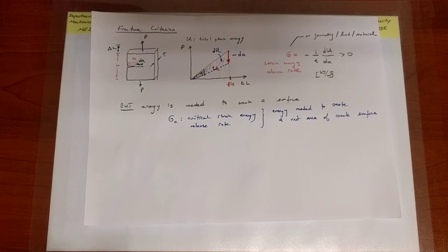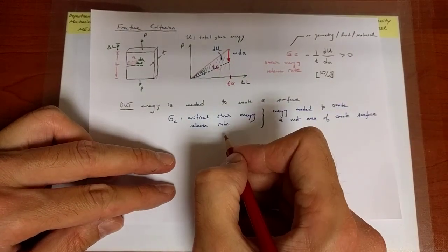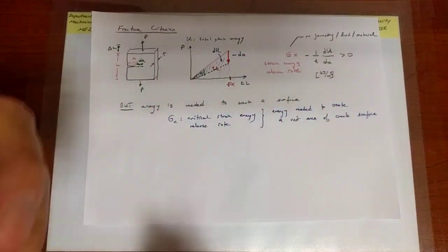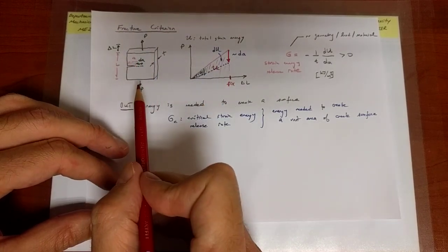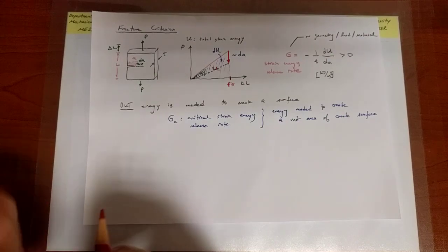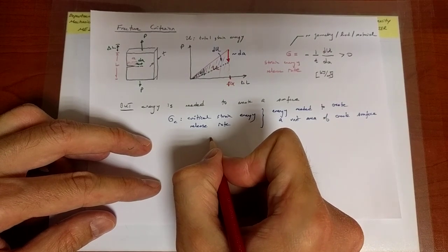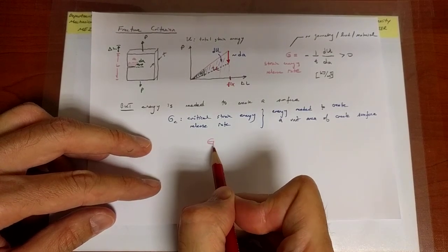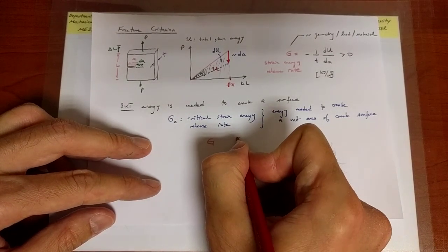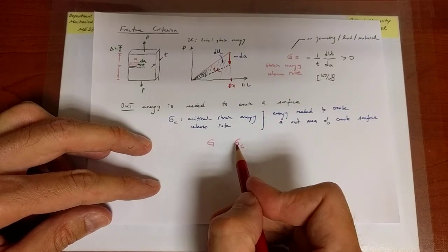Now, it turns out that the answer is already in a form that we have formulated earlier for failure criteria. We have a certain quantity that lumps many different processes that are going on. I'm loading, the thing is deforming, and there's a certain amount of energy that is being stored, and I imagine if the crack propagates, it is going to release a certain amount of energy G from the system. So that's what I have from my calculations for a given loading. On the other hand, what I have physically as a bound is GC. This is what is needed for propagation to actually occur.